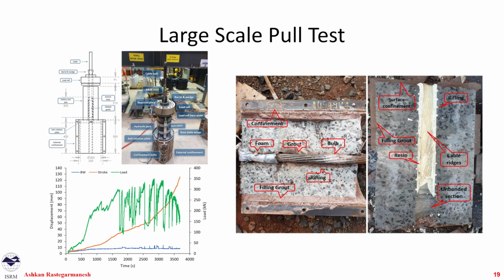After the test, we open up the samples. You can see the inside of the samples. So that's the external confinement. That's the infill grout, the concrete, which was our main confinement, our grout, our cable, that foam that I mentioned, and those holes for the bolts that we put there. And this is the same on the right. We see the same for the resin.